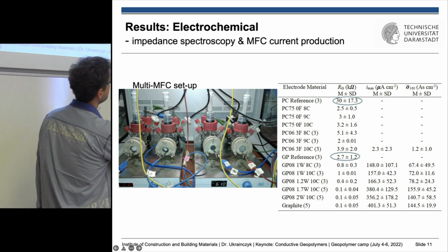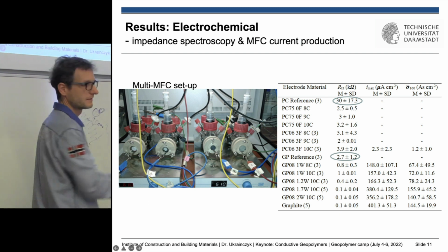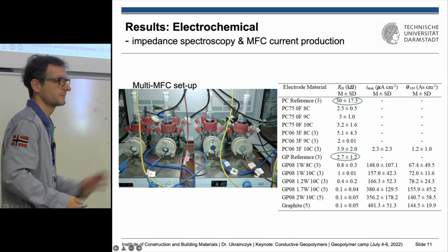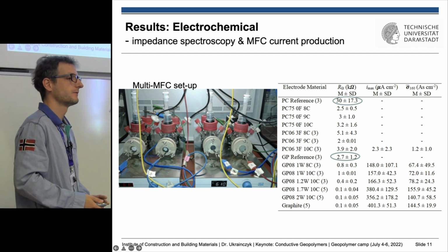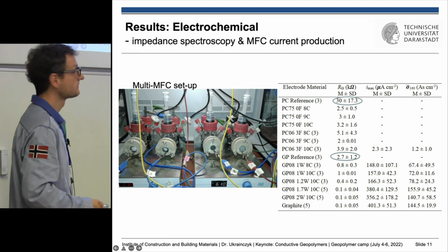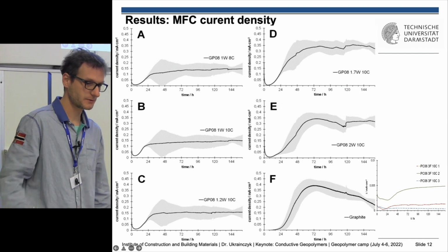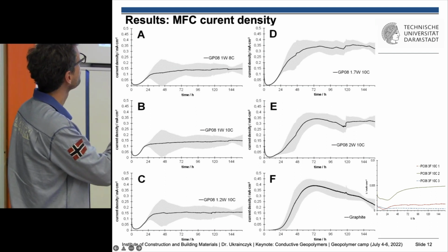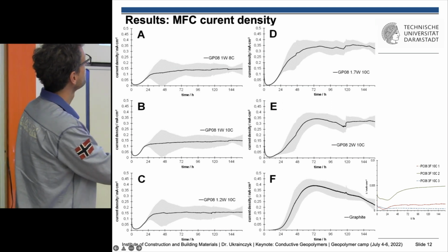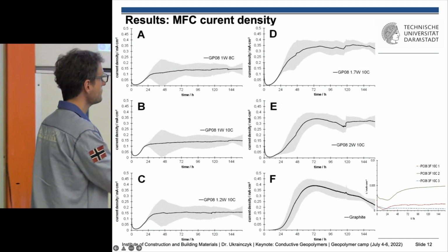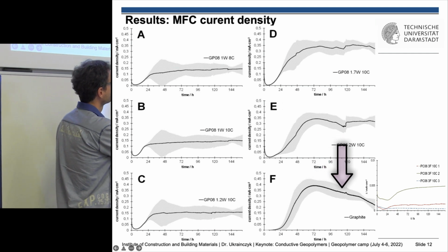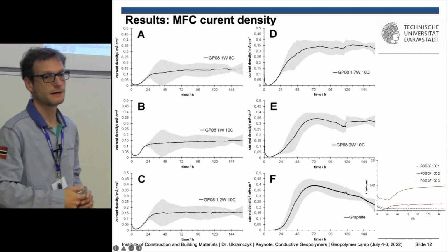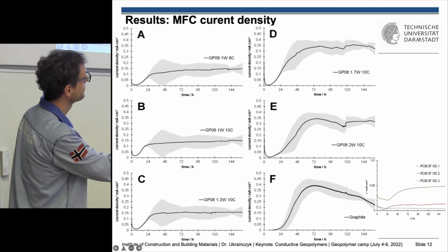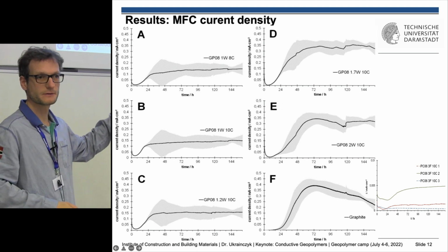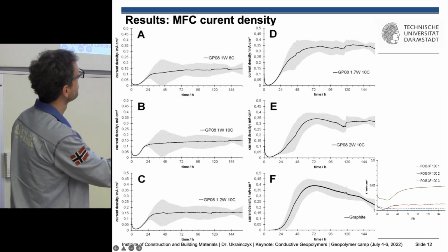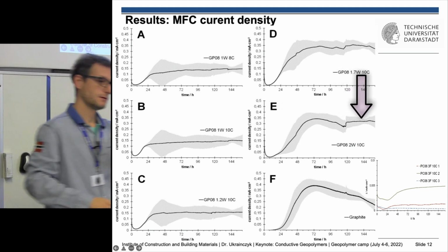So here we can see some powers. We could not directly, but that's also the question we had from the audience. But the power usually for these microbial fuel cells is half watt per square meter. Here, those are the measurements of current densities. And we can see for different amounts of carbon that during time it's quite stable. This is for the reference graphite. Here it goes down because the bacteria are lacking food. But here we added food. This is a batch experiment, but of course in reality it's a continuous flow. And here you can see when we added food, it stabilizes.